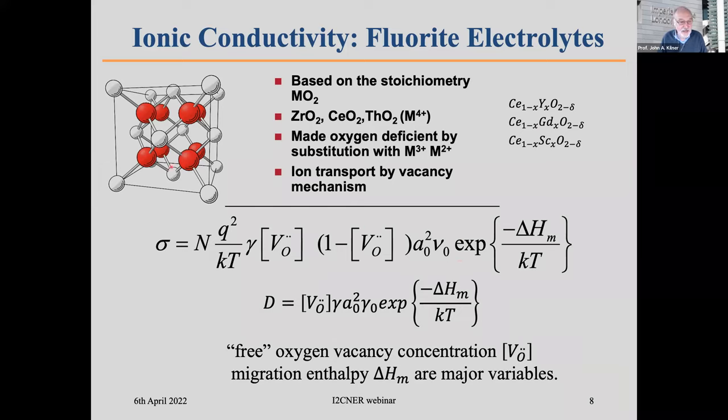And that is the amount of energy that you need to put into the system to get an oxygen ion to move from one site to the other. Here's an equivalent expression for the self-diffusion coefficient. And what really matters is the oxygen concentration of the free vacancies, those that are able to move, because some of these vacancies are put in and are actually structural vacancies and they're not free to move, and this migration enthalpy.